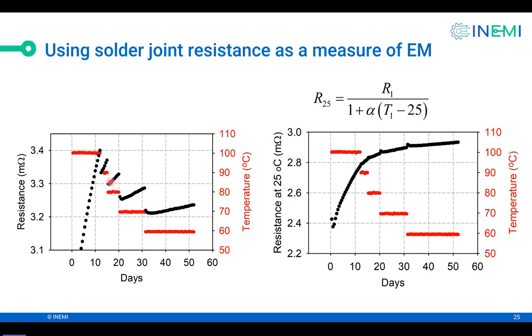So before I go there, let's talk about this drop in resistance. That happens because whenever you take a piece of metal, its resistance will decrease when you decrease the temperature. So this drop is purely because we went from 80 degrees oven temperature to 70 degrees. But since we are using resistance as a measure of electromigration, we don't want to have a temperature effect on resistance. So what would this curve look like if we were to cool the specimen, in a thought experiment, to room temperature? So on the right side, we are showing this curve, and this is what the left curve would be if we cooled the specimen to room temperature.